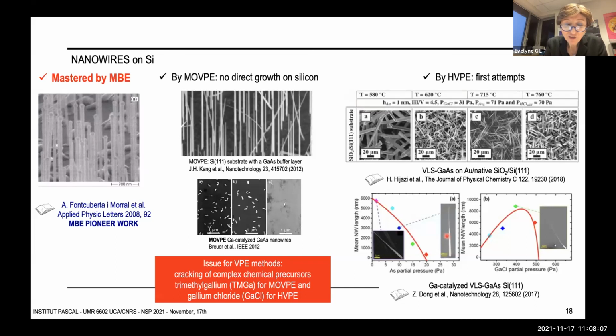As a matter of fact, the formation of liquid gallium droplets from a gallium chloride vapor phase is not thermodynamically favorable. And we believed by that time that if we submitted the silicon surface to a pre-treatment under gallium chloride atmosphere or mixed arsine gallium chloride atmosphere at low temperature, some liquid gallium droplets would be stabilized on the substrate surface, but that obviously doesn't work.